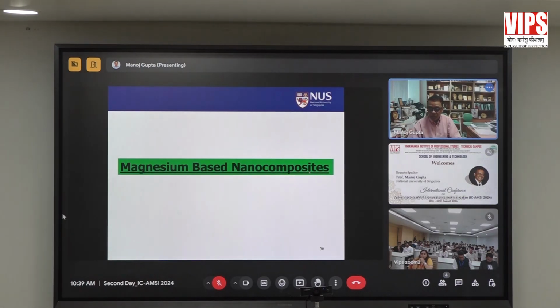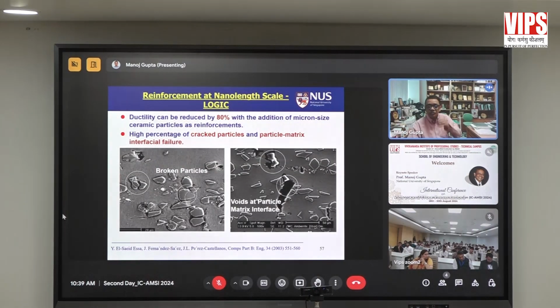Now, one of the materials on which I worked is the magnesium-based nanocomposites. In the nanocomposite, we use the reinforcement at nano length scale. Typically in the 80s and 90s and year 2000, most of the research was done on micron size reinforcement. As you see in the images here, when you apply tensile stresses, the particle can break or debond. Once the breaking and debonding happens, your properties get compromised and you are not able to realize the full fracture strain or ductility and the strength.